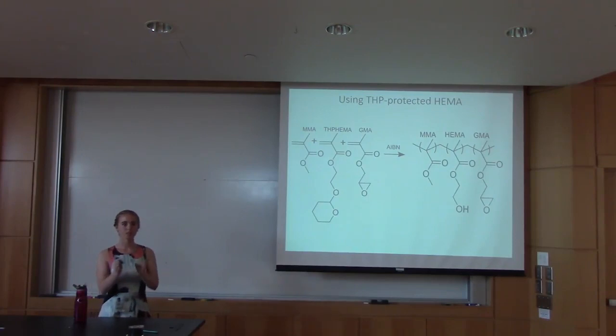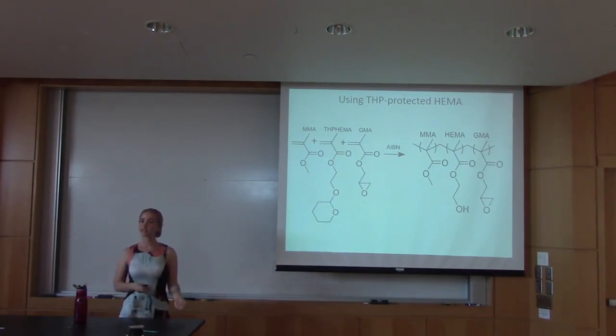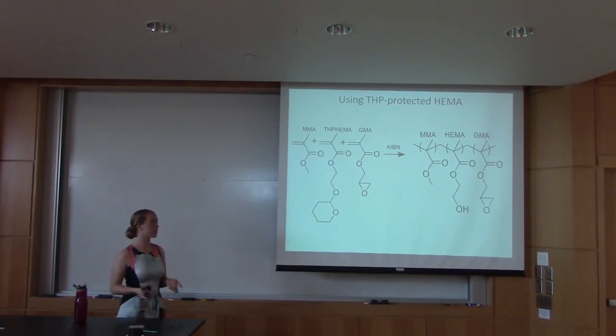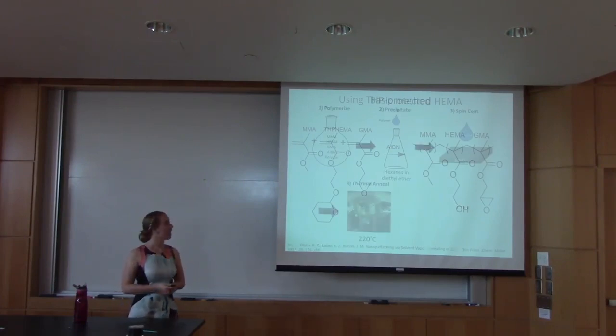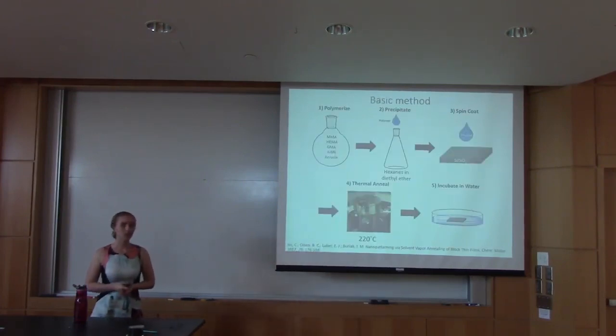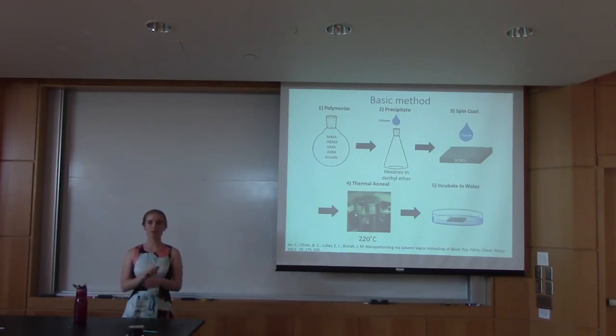And we know this because when we first tried it at 160 degrees Celsius, it did not deprotect, but when we did it at a higher temperature of 220 degrees Celsius, it did end up deprotecting. So now we have made the random copolymer we want. And the last step is to incubate it in water. So we have this wafer with a random copolymer on it, and we incubate it in water for a couple hours. Well, this may seem trivial.